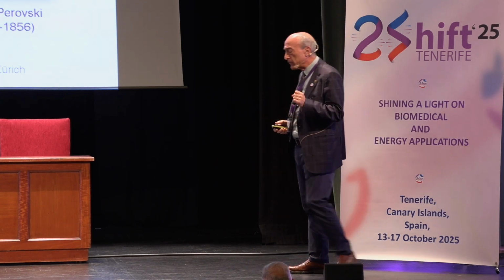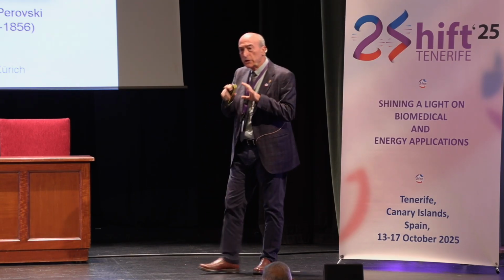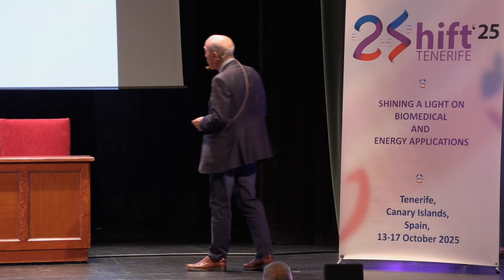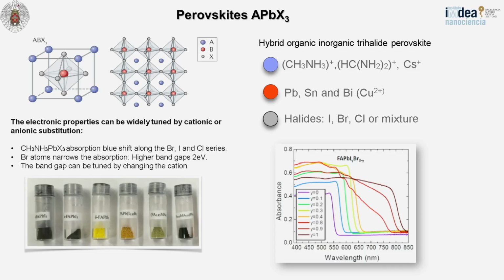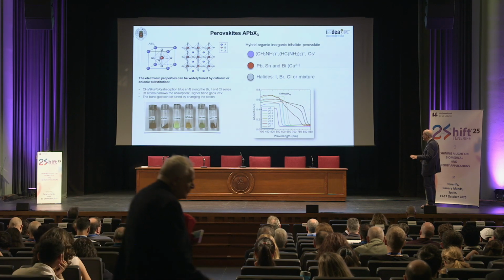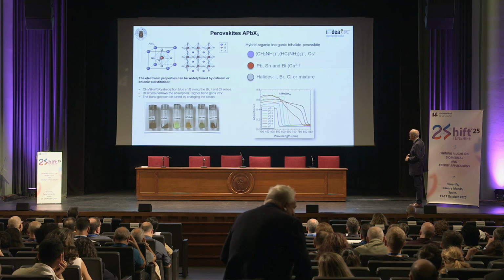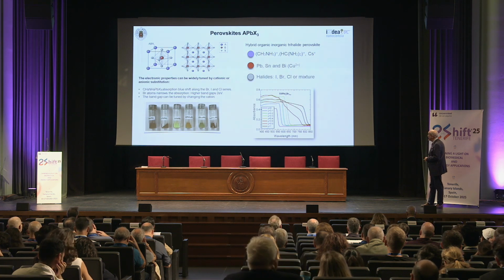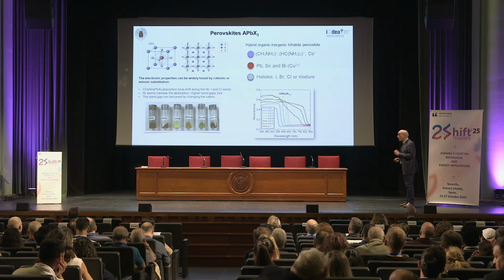The size of the cations are very stringent in order to preserve the stability of these systems. And what is amazing in these so-called hybrid organic-inorganic halide perovskites is that typical cations are, the biggest cation is A in blue, and this is methylammonium, formamidinium, cesium, although it is not organic. And the other cation B typically is lead. Cations are with 2+ charges, and tin, bismuth has been used, although not particularly very successfully for this purpose, and much more recently copper as well.